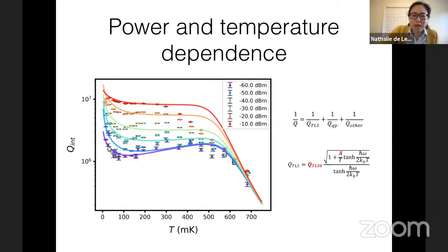So if we do a full power and temperature dependence of one of these resonators, then what we can see is that at very high temperatures, all of these curves collapse onto each other because you just have equilibrium quasi-particles from the superconducting gap of tantalum. And then you have this nice gentle slope here that actually comes from the equilibrium population of 2-level systems. And then this initial drop here with temperature actually comes from the saturation parameter of 2-level systems changing as their T1 and T2 change with temperature. So we think that everything here is pretty nicely explainable by having 2-level systems that are associated with the surface.